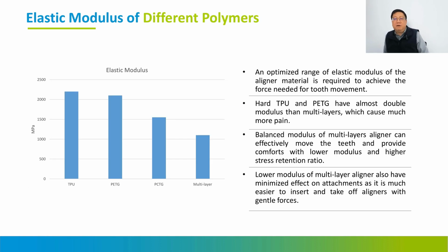If you combine different polymers, you can see the elastic modulus is quite different. For polyurethane, the elastic modulus is about 2,200. Then PETG is a bit lower, about 2,100, and PCTG even a little lower, about 1,500. Then multi-layer, because they have about 400 to 500 modulus in the middle, on average have a modulus of 1,000 to 1,200, depending on the design formulation.